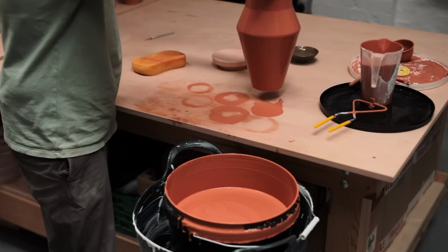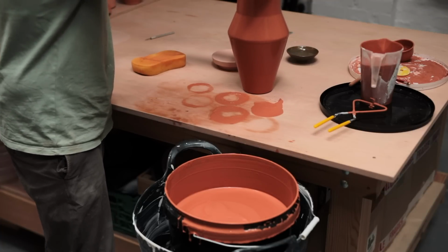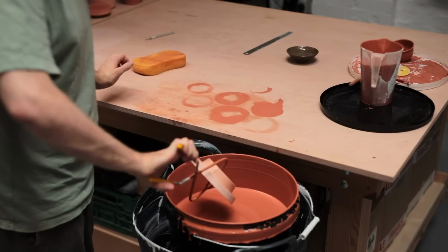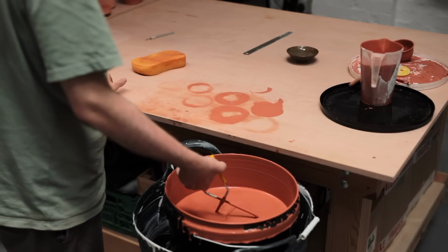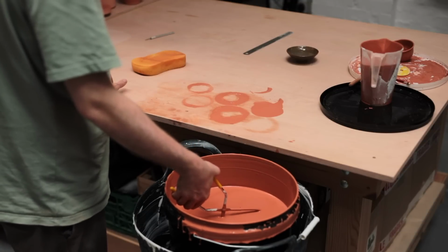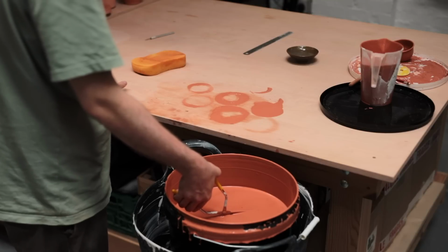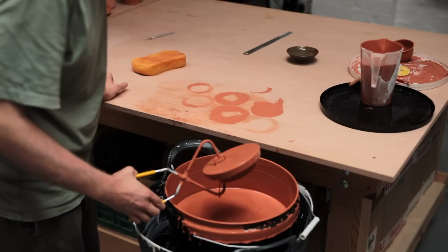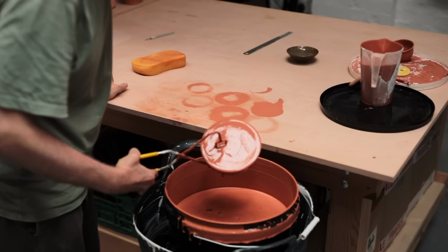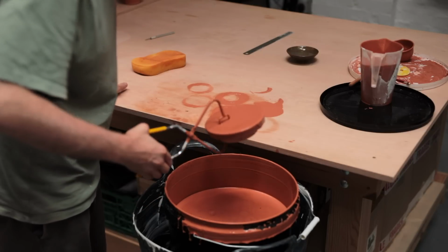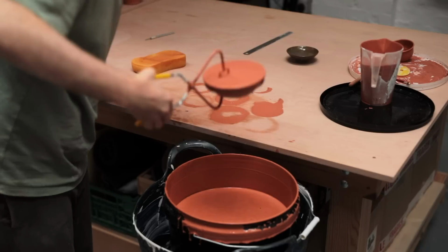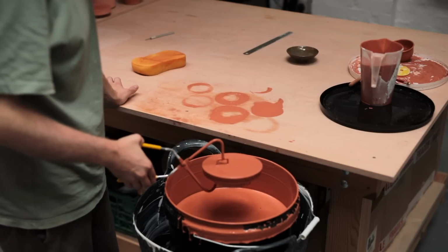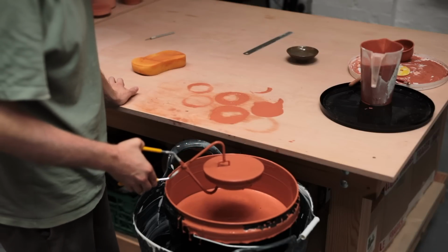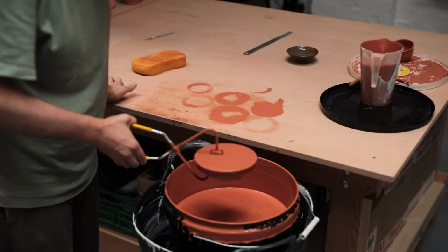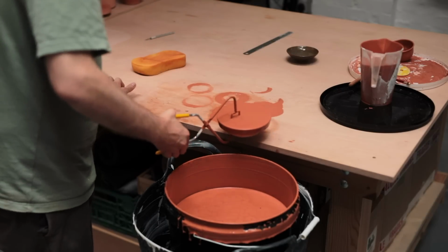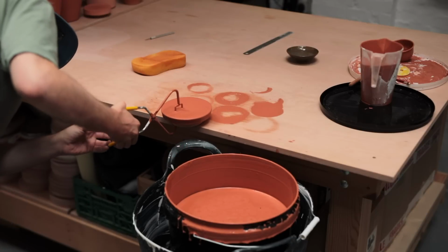Giving the pot time to dry out between coats is really important too, as the porous ceramic walls of the pot have drawn in a lot of water after being glazed, and they're pretty much saturated. This means that if I were to attempt to glaze the inside as soon as the outside layer was dry, the walls of the pot would still be saturated with water, which means inside, as no more water can be taken into the walls, only a very thin skim of glaze would end up adhering to the interior, if anything. And in all likelihood, the entire pot would become completely oversaturated and the glaze simply won't dry, resulting in glaze that flakes and cracks off the pot before it's even been fired.